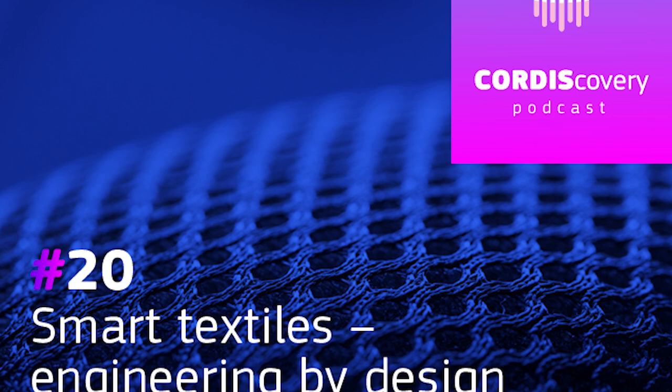Well, we used a process known as electroless copper plating. That's a very well-known process in electronic manufacturing, and in particular printed circuit board manufacture, to achieve electronic connectivity. Now, this process requires a catalyst, and wherever you want to get your copper deposited, you need to put your catalyst. So that is very useful if you want selective deposition.